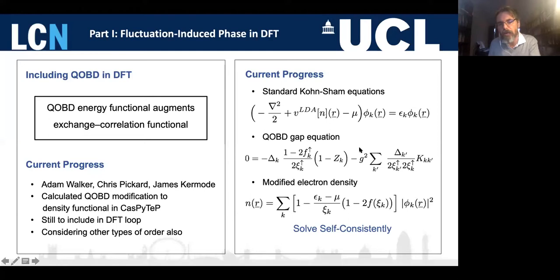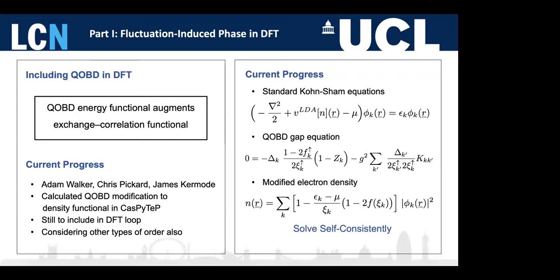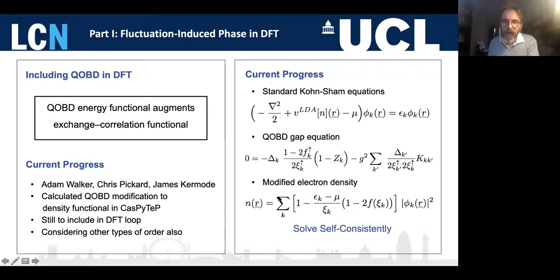So this gap equation, you can view this as the first differential with respect to delta of some free energy function. In fact, the nonlinearity of these equations is that this dispersion here is the dispersion in the background of the superconducting order. When you're calculating these Kohn-Sham equations, you have to allow for that modified electron density that comes out from having this dispersion modified by the superconducting order parameter. So in our case, you have to optimize this delta, and then you have this additional equation to solve self-consistently for the Kohn-Sham equations.